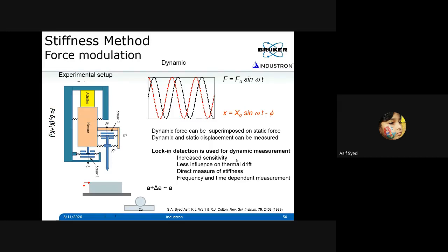For example, when you do this on an elastic material, for the force you apply and the displacement you measure, there won't be any phase shift between these two. The phase shift will be zero. But a viscoelastic material tends to have a phase shift. The degree of phase shift gives you an idea of the viscosity of the material.